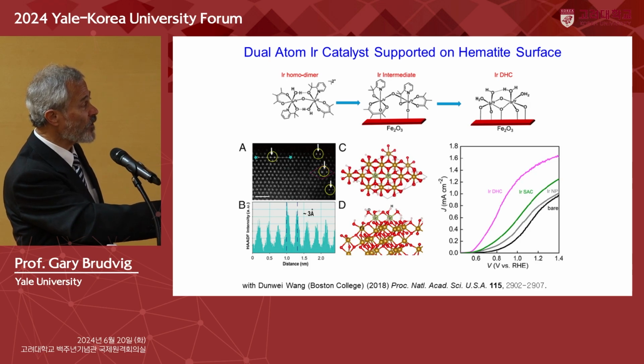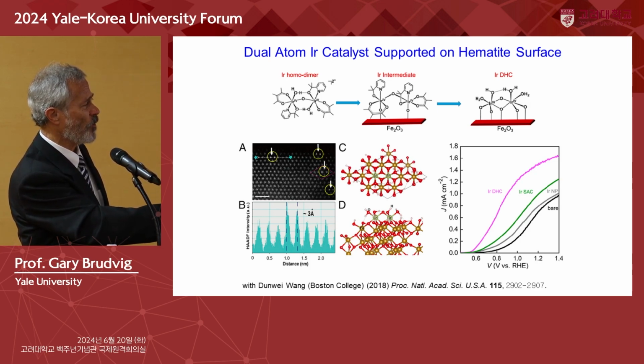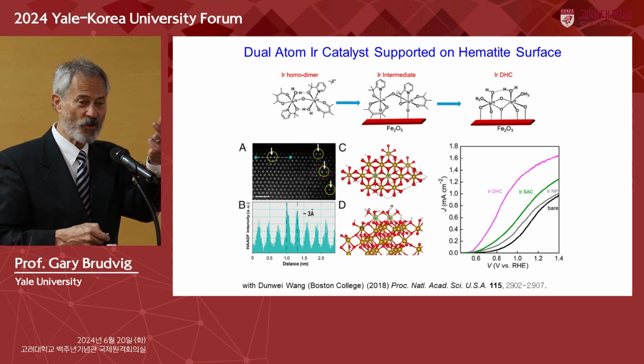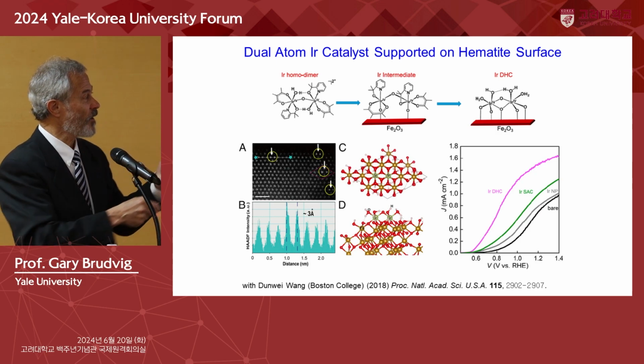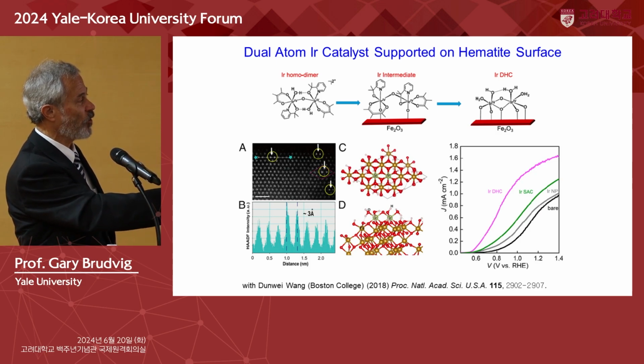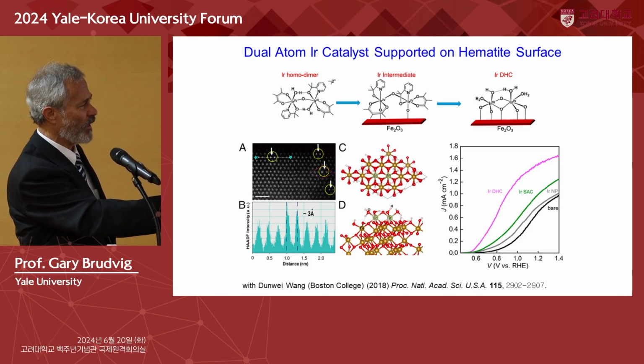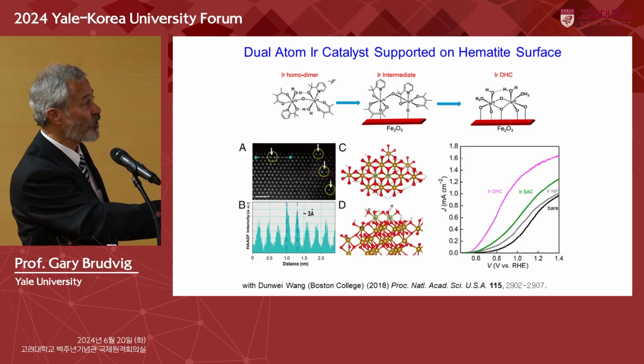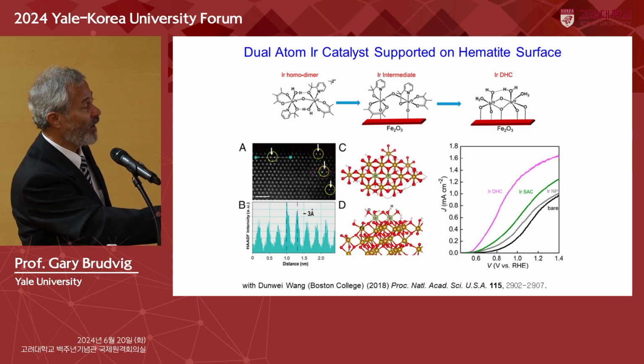And so what we think is that this iridium dimer is laying down side on into a position that's immediately above an iron atom on both positions. And interestingly, this is a site where there are 3 oxygens on the surface that are in a position to coordinate the iridium, and they're spaced exactly at a separation of the iridium dimer. So we think the iridium dimer is laying down side on to produce a side-on bound catalyst, and it's still catalytically active on the surface.